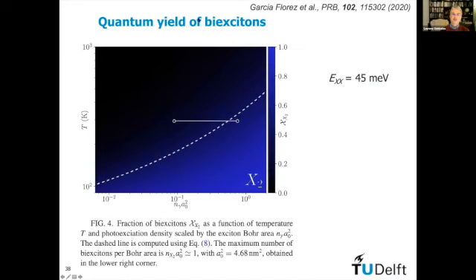Now then, something about the quantum yield of biexcitons. You could say, when I have so many excitons present, are they going to bind together and form a biexciton like a hydrogen molecule? From experiments, we inferred a biexciton binding energy of 45 millielectron volt, and we did theoretical calculations with all the statistical thermodynamics involved. We can see that at room temperature, in the range where we did our experiments, that is the number of photons per Bohr radius, or the number of photons per nanosheet, at the highest density we have about 60% of biexcitons. But if you would cool down the sample, then we would get close to 100% biexcitons.